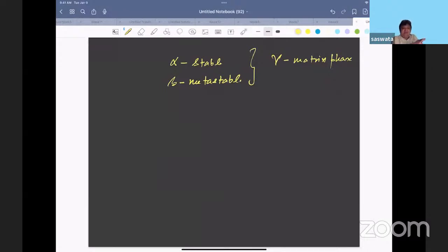So now there is one point. Basically, is it that Cr23C6 has to decompose to Cr7C3, or whichever phase you are telling, or is it that it dissolves and another phase forms? Have you looked at that? Yeah, usually what people say is that cementite to Cr7C3 is more or less an in situ transformation, that Cr7C3 forms by a rearrangement of the atoms within the Fe3C cell. Okay, so that's an in situ transformation. Whereas Cr7C3 to Cr23C6 is more like dissolution and reprecipitation.